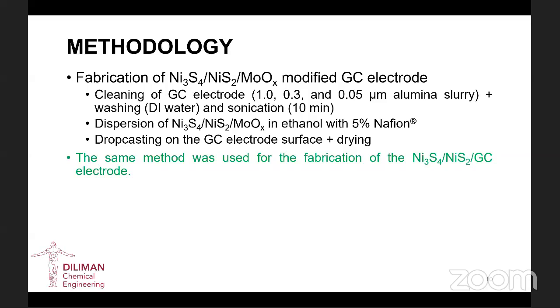And this dispersion was drop casted on the glassy carbon electrode surface with an area of 0.0707 square centimeters. And this was dried under ambient conditions. So the same method was used for the fabrication of the modified electrode without the molybdenum compound.